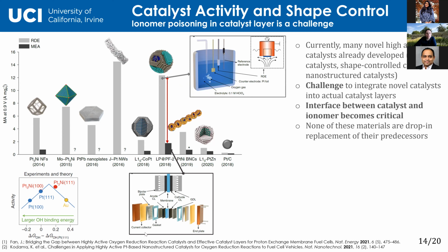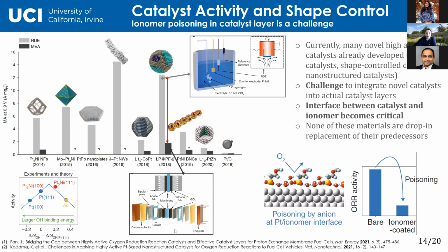And this has been a mystery. And this is something the field has been working on to explain. Why do we have this huge reduction in mass activity the moment we integrate this beautiful catalyst into membrane electrode assembly? And part of the problem is that the ionomer has the sulfonic acid groups. They're negatively charged, they adsorb on platinum and they poison the surface and they block oxygen from reaching the surface.